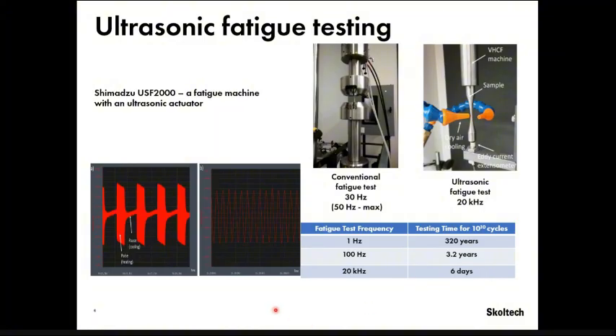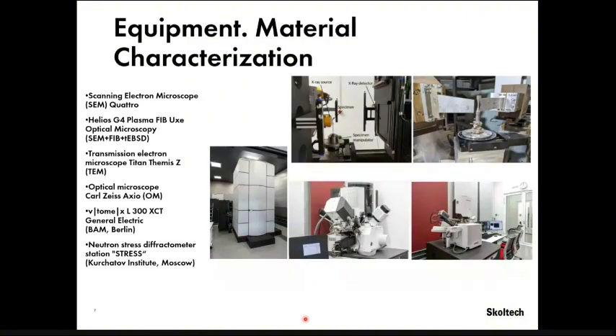We also use a pulse-pause regime to get additional cooling during cycling, because due to resonance the specimen can heat up, and we also cool our specimens with a dry air system. And we used advanced material characterization equipment like microscopy and also X-ray computer tomography. One of the main tools is the machine for neutron diffraction stress measurements, which is at the Kurchatov Institute in Moscow, and we used it for residual stress measurements, which allows us to measure residual stress in the bulk of the material.